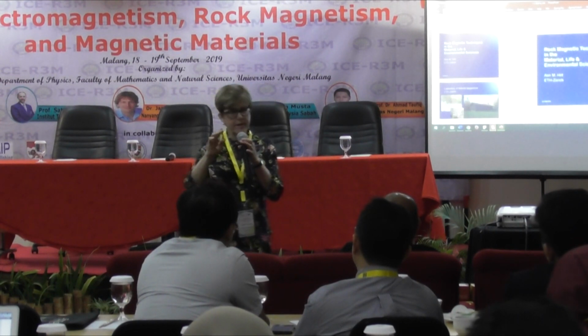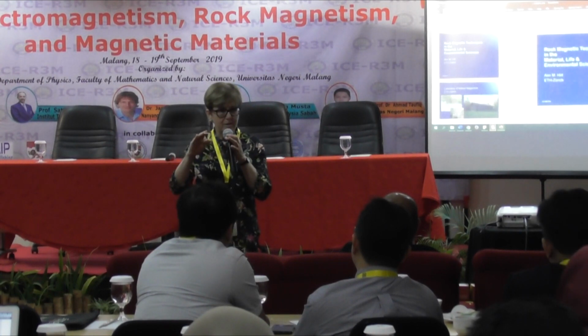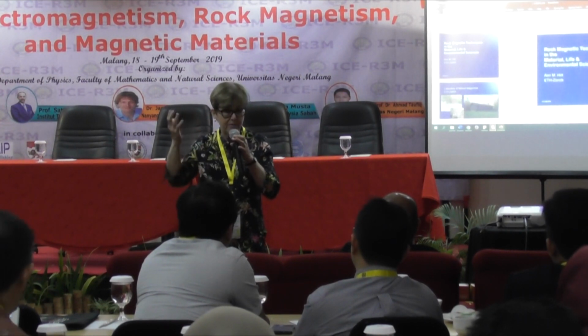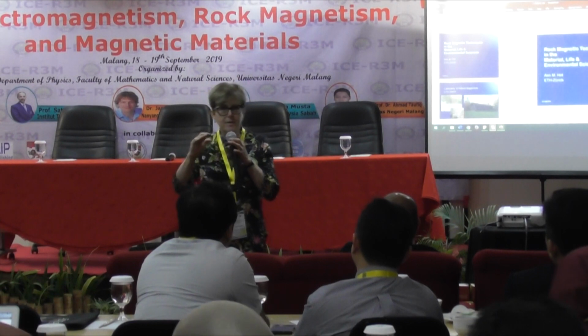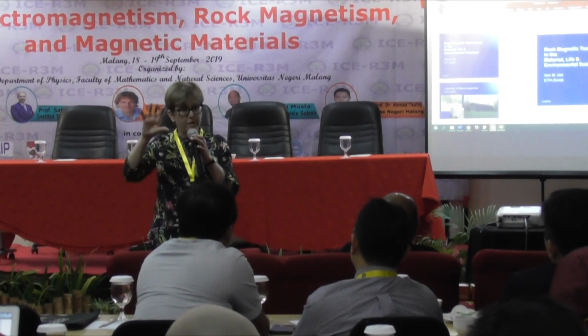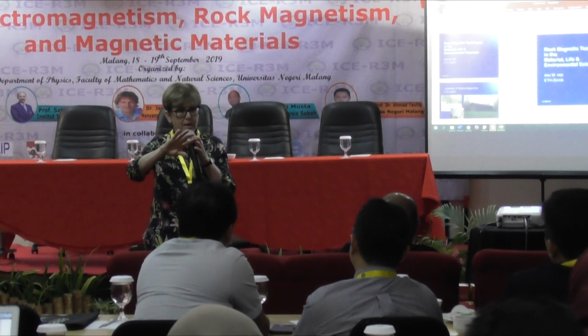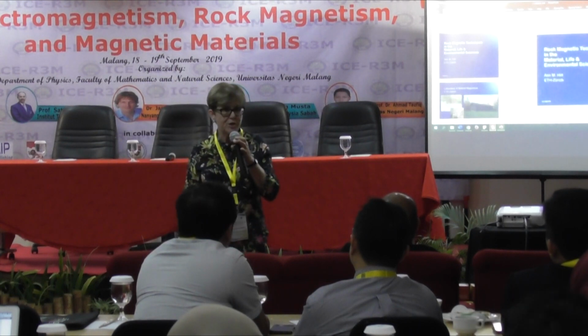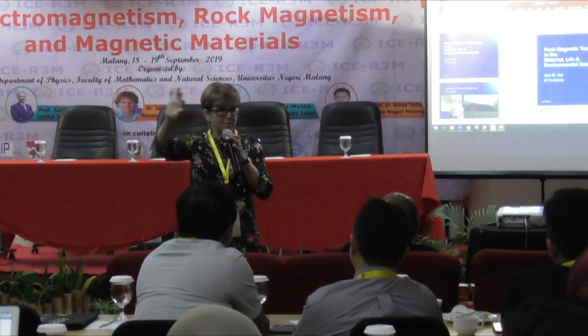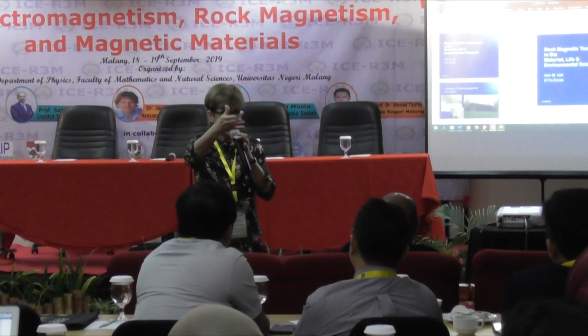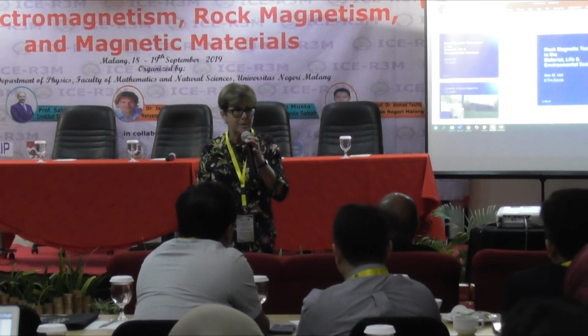Now, iron hydroxide has a fairly high susceptibility. It's not as high as magnetite, which is ferrimagnetic. So what we think is happening is the arsenic is binding with the iron hydroxide, and that's why we're seeing a good correlation. When we look at iron, we have this one plateau at 4% iron, and that probably has the magnetite and other minerals in there.